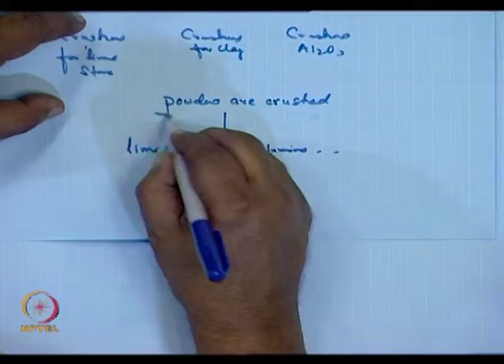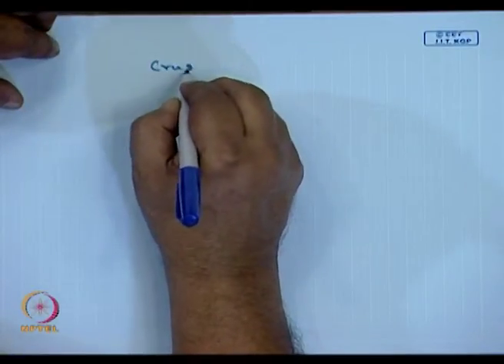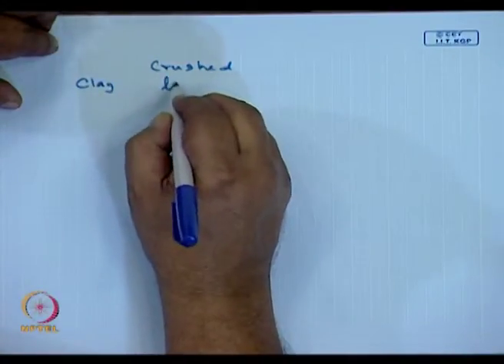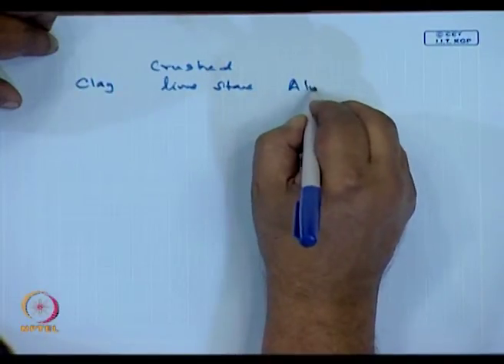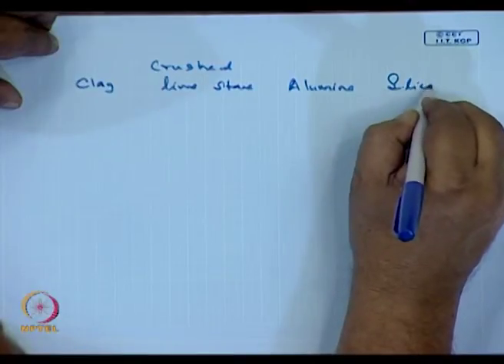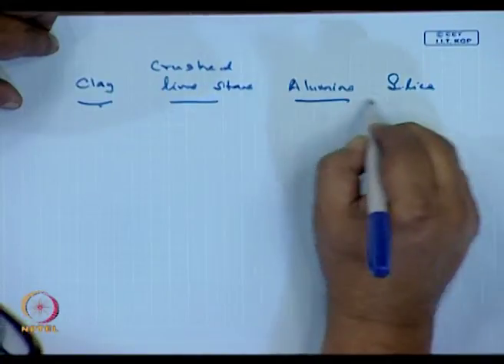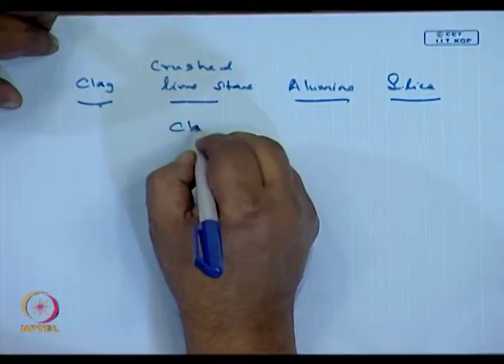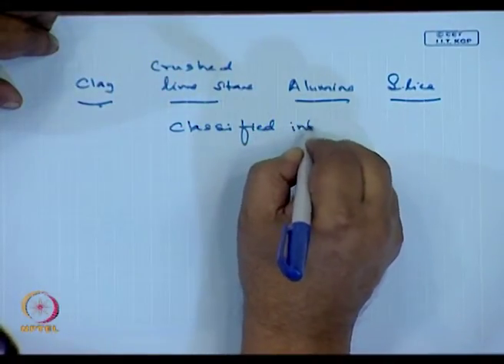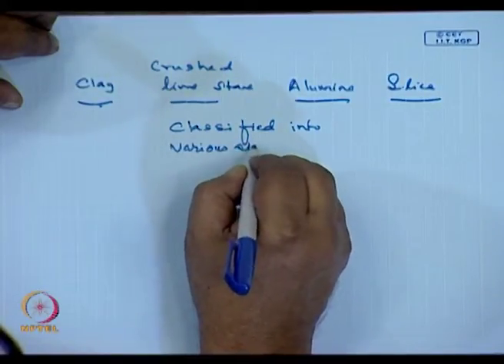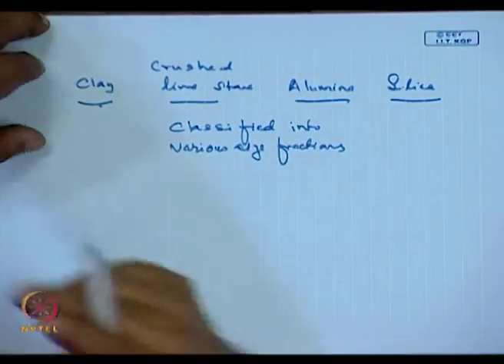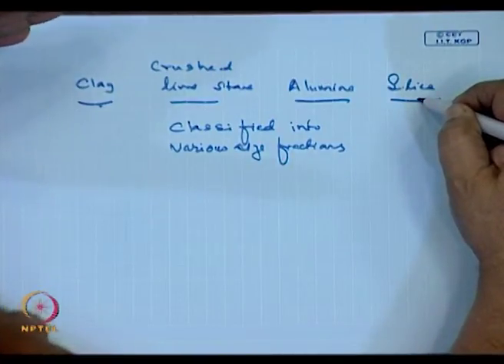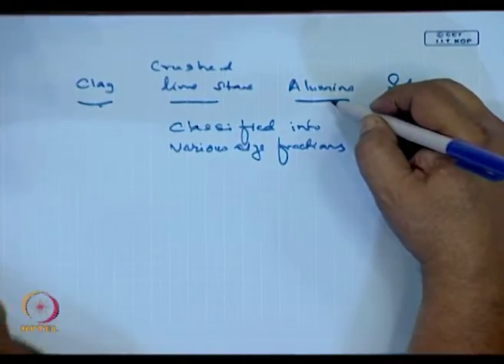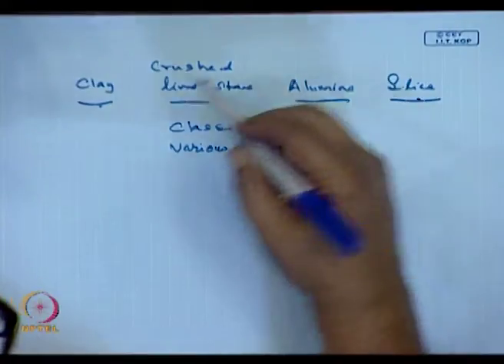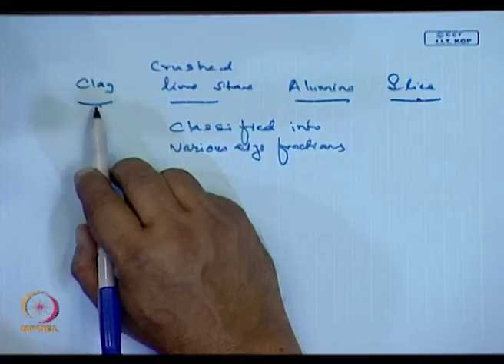First of all, each of these crushed powders, clay, limestone, alumina, silica, is first classified into various size fractions. You have to realize silica is very hard. So, chances are, even though we are using the same mill, powder sizes of the silica grains may be larger. Alumina is obtained from bauxite, that is much softer. Limestone is soft, clay can be hard or soft depending on the source.